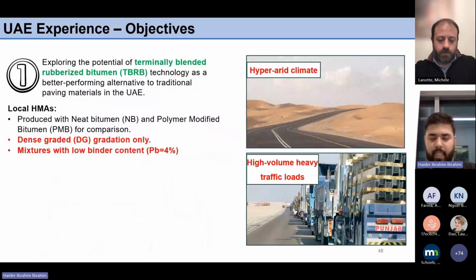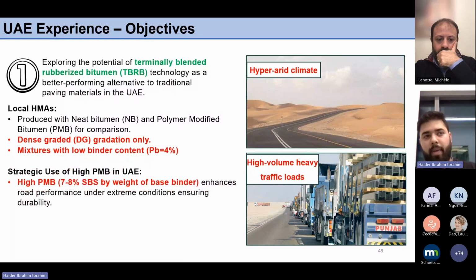On the other hand, the asphalts used here in the UAE are very peculiar and are characterized by a dense gradation and a low binder content of around 4%, which is around 1.5% less than what Dr. Angela mentioned. And in order for us to introduce a new bitumen in these conditions without altering the volumetrics or the mix designs, we needed a smooth, uniform binder. And this was also one of the reasons behind choosing the TBRB instead of the typical wet process modified rubberized asphalt. Before our project, the UAE was moving from HMA with neat bitumen to HMA with high polymer modification of around 7% by weight of the base binder, because of the fact it's a hyper-arid climate, as I mentioned earlier, and the conditions are challenging.